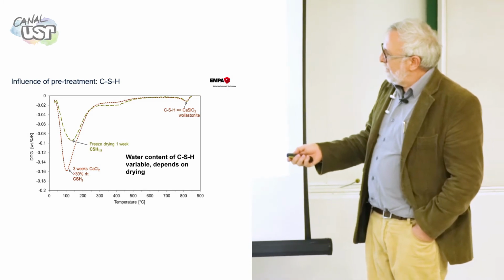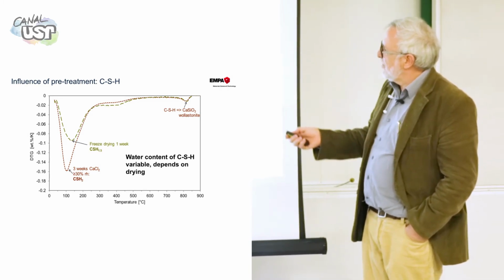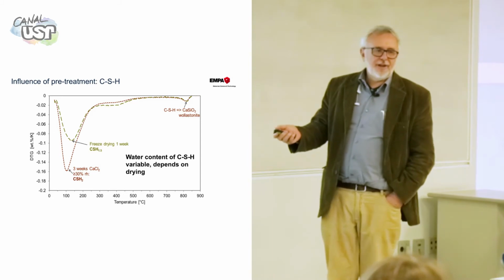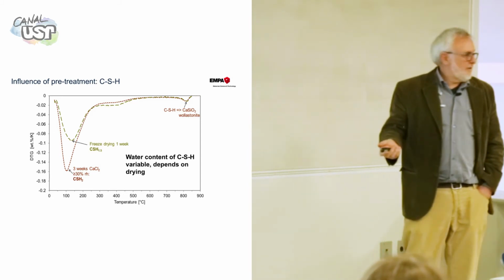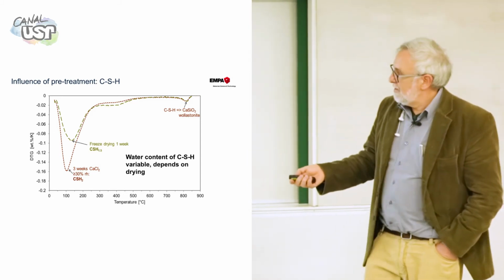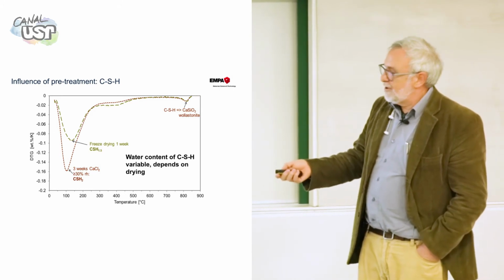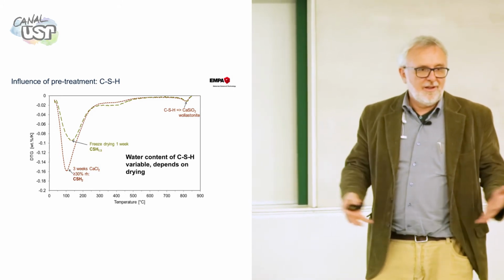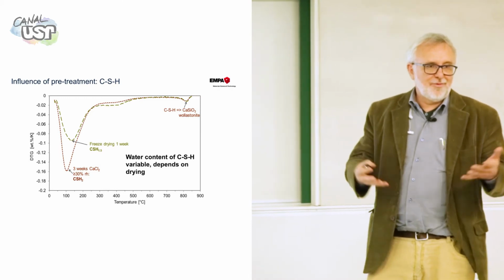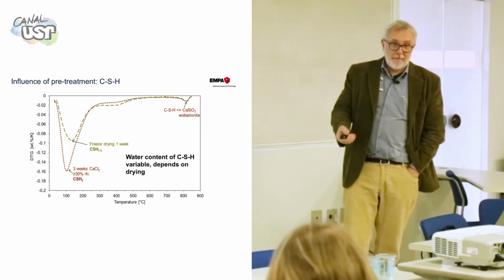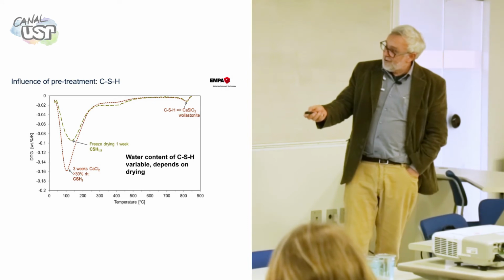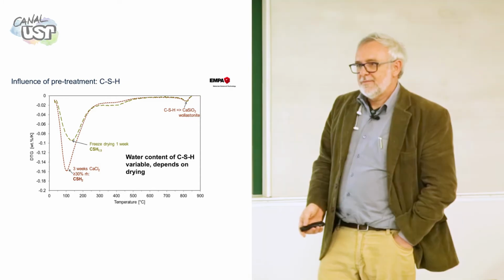And if you try to recalculate, this is CSH, probably hydrated, produced by hydrating only C3S or something. So it's pure CSH. And you know the stoichiometry because you know the reaction, that's only calcium and silicate to react, and you put water, so you know things, it's not cement. This is what you lose, 0.5 molecules of water just by doing freeze drying. And this is about CSH, it's like ettringite, it's very difficult to measure.